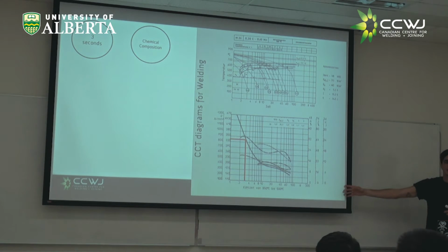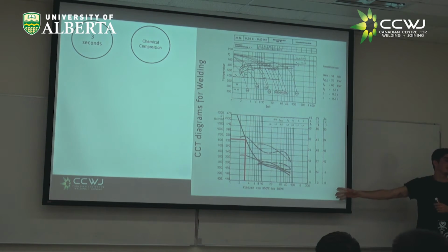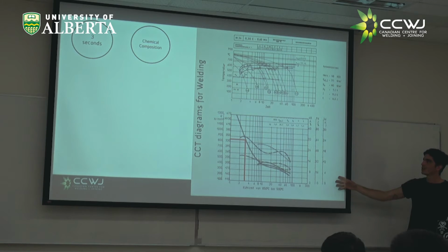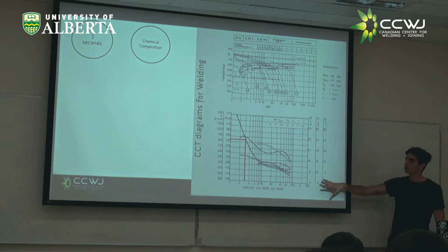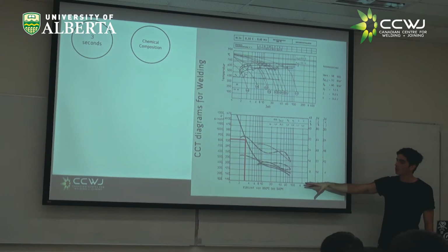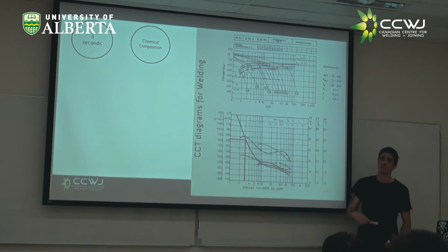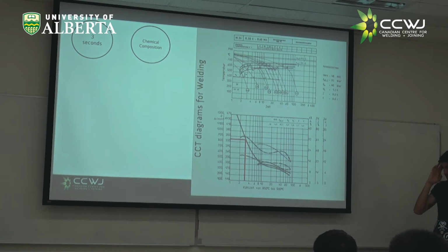So what I have here is just a page of my CCT atlas, the German atlas that I told you about. There is a copy at the U of A of the new edition, if someone is interested in seeing many CCT diagrams. But basically what you have is a real CCT, like the ones Dr. Mendes showed you in class, and this is information from that CCT. Basically, it shows how the mechanical properties change with the cooling rate. If you look at this line, that's our hardness, and that's what we're thinking about.